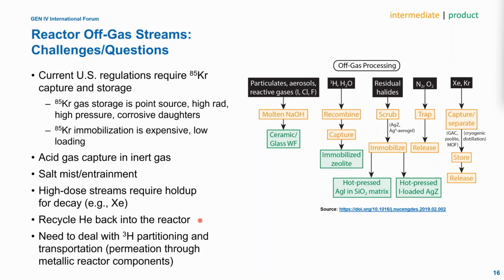You've got helium that needs to be recycled back into the reactor, and I'll show you a concept where a lot of this can be addressed in a single system, which is a molten hydroxide scrubber. And then you need to deal with tritium partitioning and transportation. So hydrogen can permeate through metallic reactor components, and this needs to be considered. So this is a very unique thing when you think about dealing with off-gas from, say, used nuclear fuel reprocessing. This is quite different, where we've got lots and lots of things such as aerosols, particulates, reactive gases, dusts, and things that need to be addressed before you start trying to capture things downstream. And so you've got an option for a molten hydroxide scrubber, and I'll talk about that later.